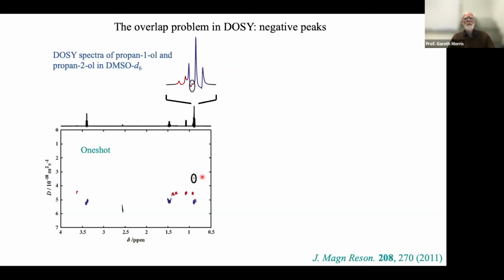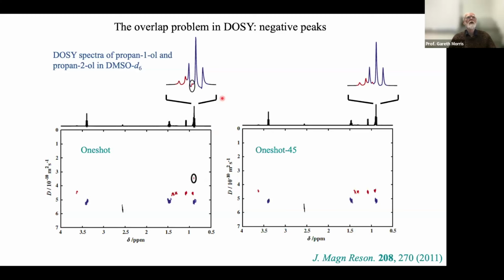So if we see a really oddball result, it's always worth thinking, is our spectrum really purely in absorption mode? Now, fortunately, where we have J modulation, because we've been greedy with our gradient pulses, there is a way around the problem, which is to add a 45 degree purge pulse. So if we just stick a 45 degree pulse on the end to turn our dispersion mode signals into multiple quantum, then everything lines up again as well as we normally get in DOSY.